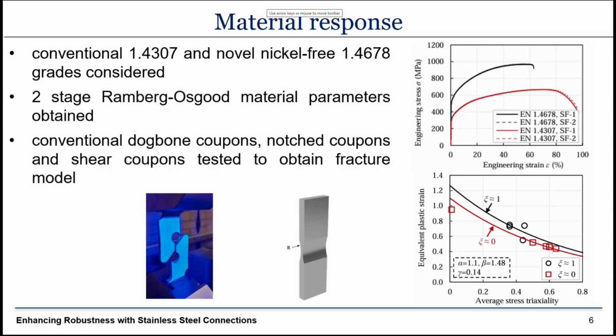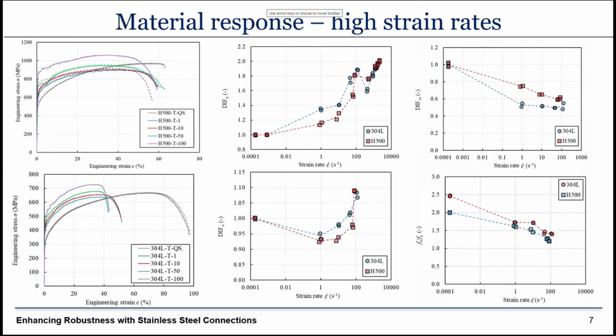So in addition to the tests under more static loading conditions, tests were also conducted at high strain rates, and here are the results for standard coupons. So for the novel H500 nickel-free stainless steel coupon, we can see that with increasing strain rate, the black curve corresponds to quasi-static conditions. And then progressively, we increase the strain rate to 100% per second, then 10 times more than that, and so on, until 10,000% per second. And we can see with increasing strain rate, we get a reduction in ductility, so reduction in strain at ultimate stress, but a significant increase in the nominal yield and the ultimate tensile stress for very high strain rates. For the conventional stainless steel 304L, we get a more marked reduction in ductility.